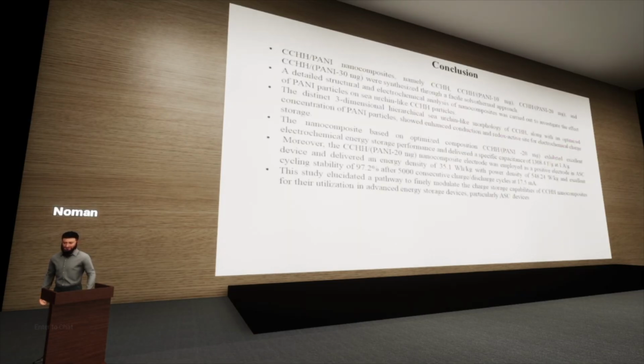So the conclusion of the work was that we made four different compositions of the cobalt carbonate hydroxide hydrate with polyaniline, and the 20 milligram addition of polyaniline showed the maximum results for the supercapacitor electrode material. Then that electrode material was used as a positive electrode, and an asymmetric supercapacitor device was formed. The supercapacitor device shows the specific capacitance of 1308.4 farad per gram at 1 ampere per gram.